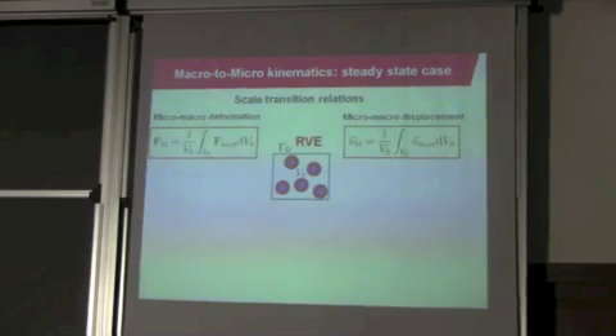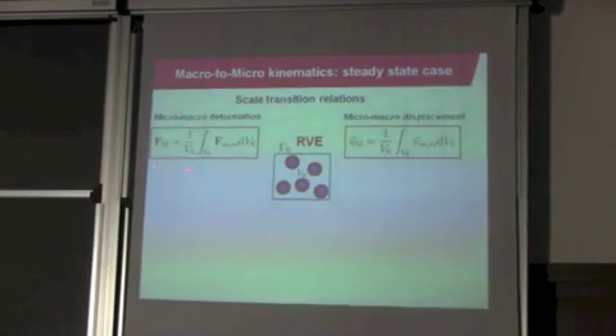Okay, then I write the scale transition relations, which are typically the requirement that the volume average of the microscopic deformation should give me the macroscopic deformation, from where, after very simple mathematics, I can conclude that if I require this microfluctuation field to be periodic, I can ensure that this condition is satisfied. Now, in addition to that, I will add one more condition, which is usually not needed in the quasi-static computational homogenization, but I will need it later on, which is I will also require that the volume average of the microscopic displacement will give me the macroscopic displacement,